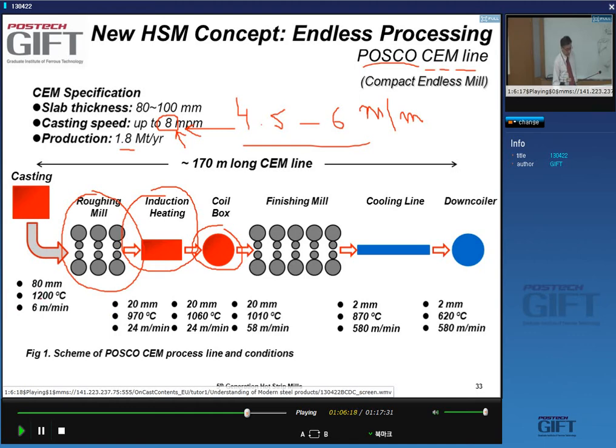And these are some typical production numbers, okay? The casting speed is not normally 8 meters per minute, it's closer to 6 meters per minute, yes? And you can see here what the type of reductions you have. As expected, because you have a roughing mill, the thin slabs are not as thin as you can in principle cast them. They're 80, so they're on the thicker side of the compact strips, 80 millimeters, and products are thin, okay, 2 millimeters and less. Okay, so that's a far cry from the 5 to 6, typically 6 millimeters that are being produced in a conventional hot strip mill.